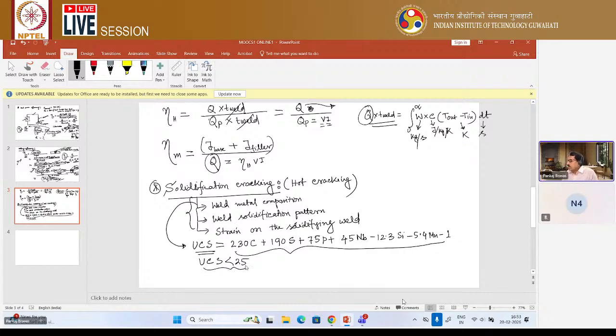Here one thing you can observe: higher carbon percentage, sulfur percentage, phosphorus or niobium are generally responsible for promoting the UCS. That means if C increases, sulfur increases, phosphorus increases, Nb increases in your weld joint, then your UCS also increases. So if the sulfur, phosphorus, niobium, carbon percentage is more in the weld joint, there is a chance of higher UCS, and a chance of higher solidification cracking. This you should keep in mind.